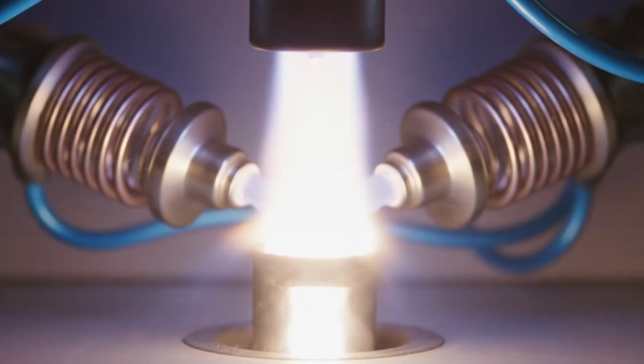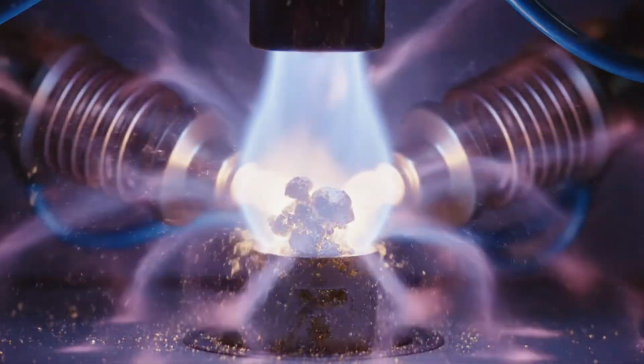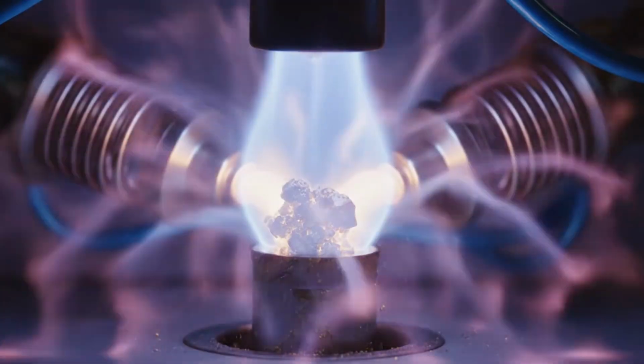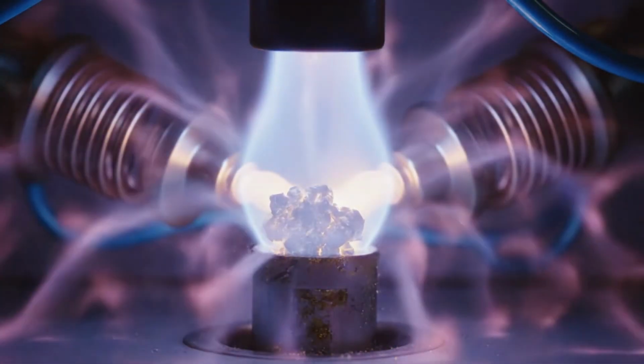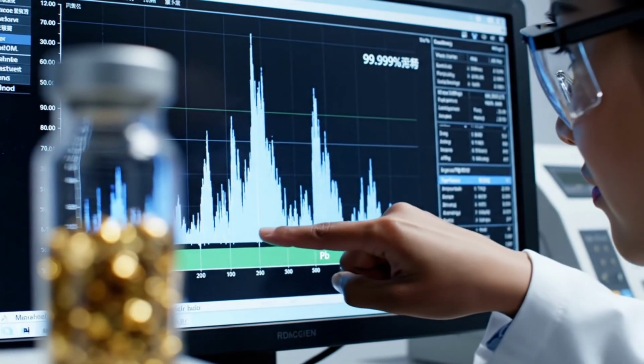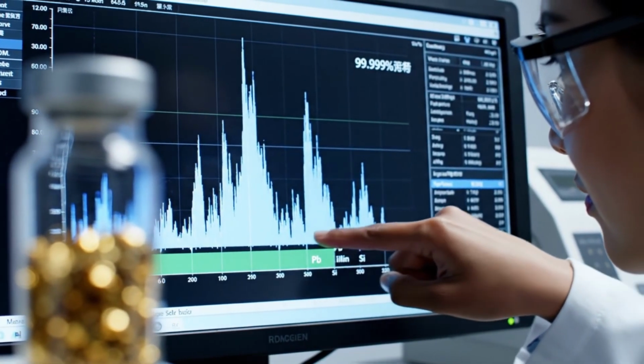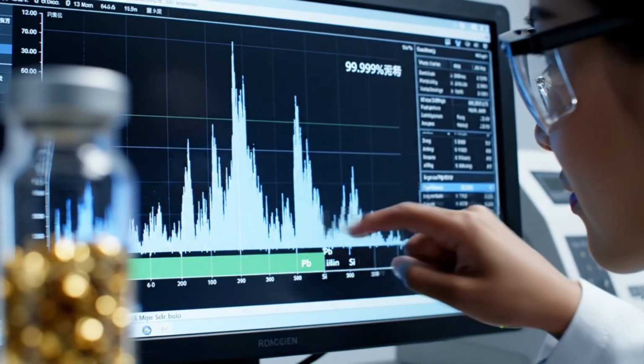Every batch of grain undergoes spectroscopy, where we burn a sample in plasma to analyze the light spectrum and verify that no impurities have slipped in. Even a trace of lead or silicon could ruin a jeweler's casting, so our purity standards for grain are as rigorous as for the investment bars.